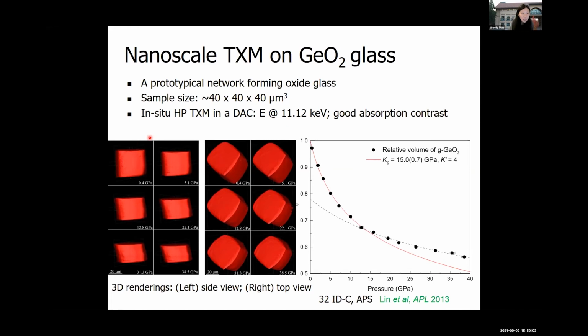Okay, so she used FIB to cut 40 by 40 by 40 cube of GeO2, and then we did the imaging at different pressures, and then these are some 3D renderings at 0.4 up to almost 40 GPa. So we can use the results to get a pressure volume relationship. And so what we find is that the density data appears to display a continuous trend to the highest pressure, but there's a change in compressibility around 10 to 13 GPa. And this complements XRD data that we had previously collected on GeO2 at high pressure, where we found that GeO2 undergoes a coordination change from 4-fold to 6-fold around this pressure.